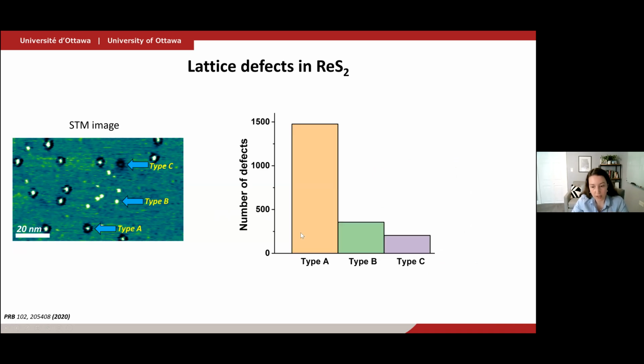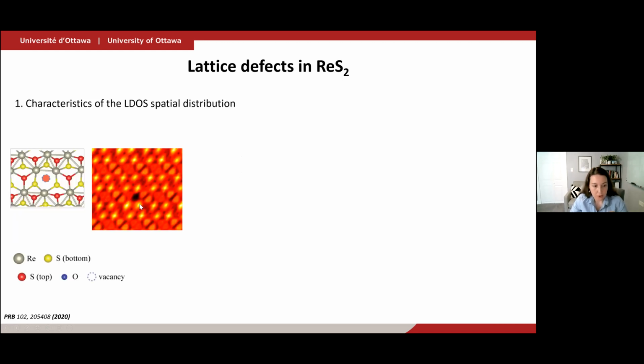And we diligently count their numbers. We find that the most common one in this material is so-called type A. And we try to exploit what is the nature of this defect. And to do so, we paired up with our theory collaborators, both at Ottawa, Professor Harlech's group, but also in Europe with Professor Francois Peters.